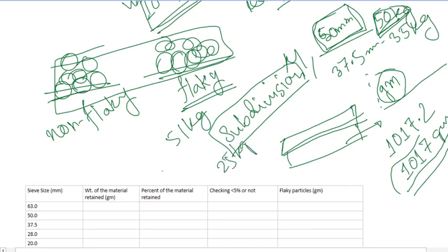So you cannot take one of 30 kg and another one of only 21 kg. Each subdivision must be greater than half of the specified size for this subdivision. So from there you can get an idea how many subdivisions might be required.